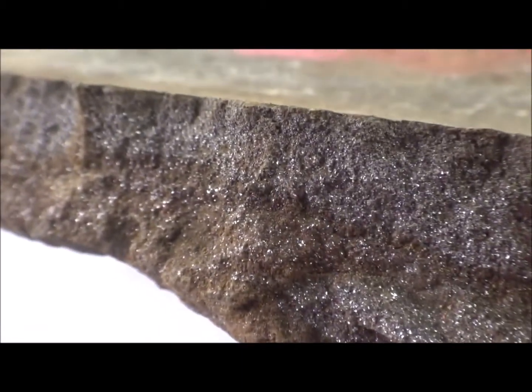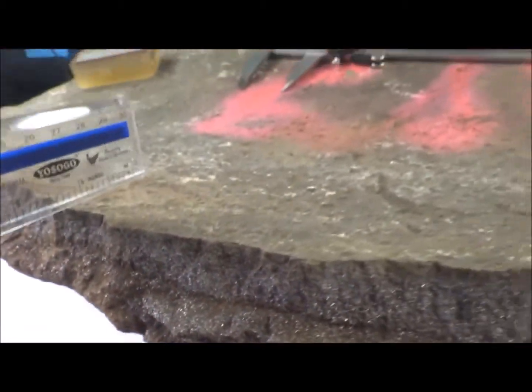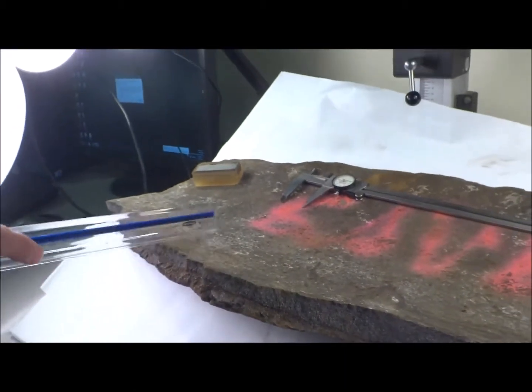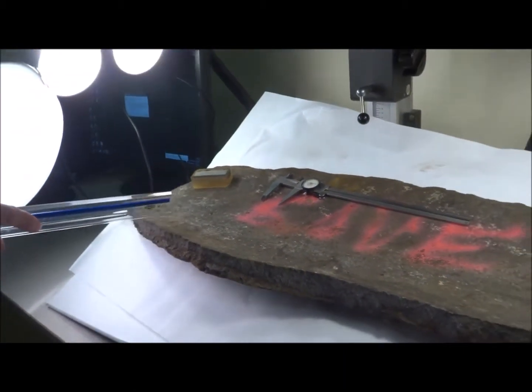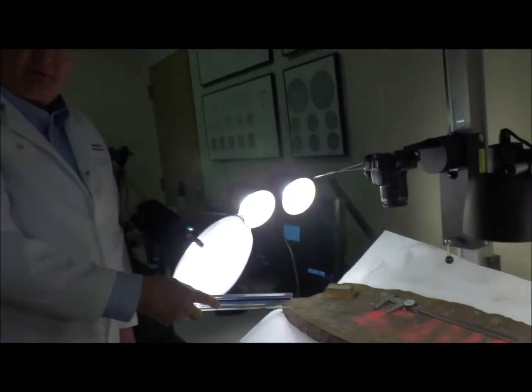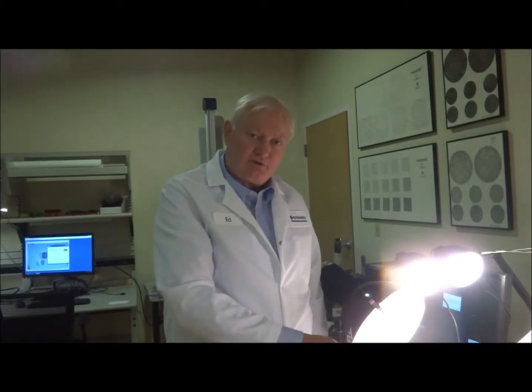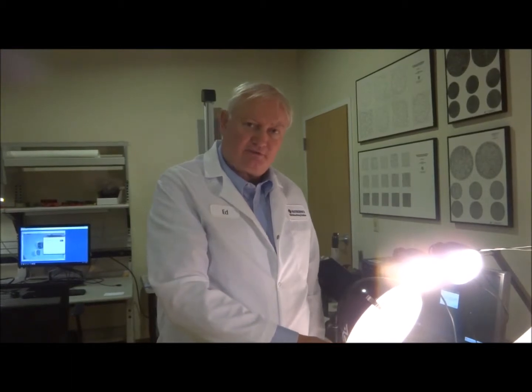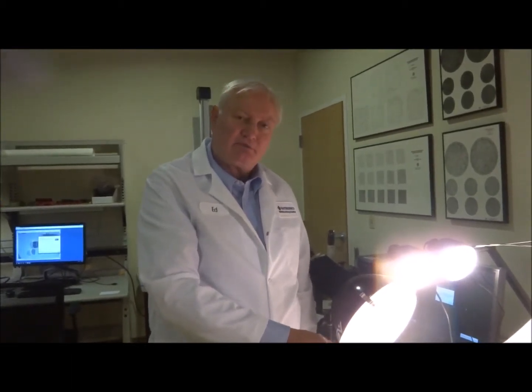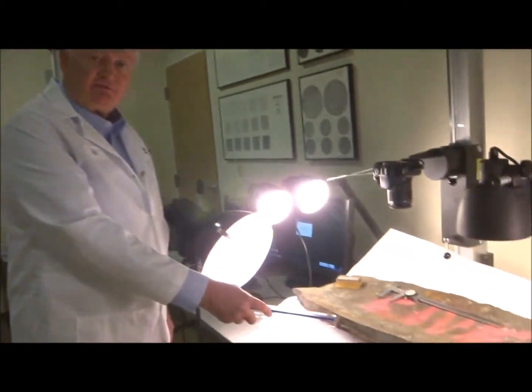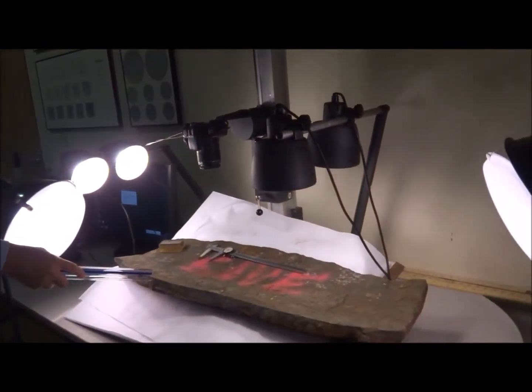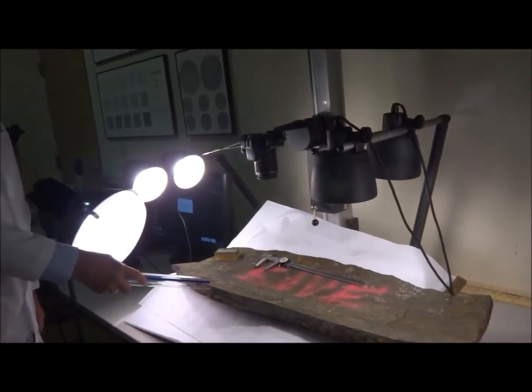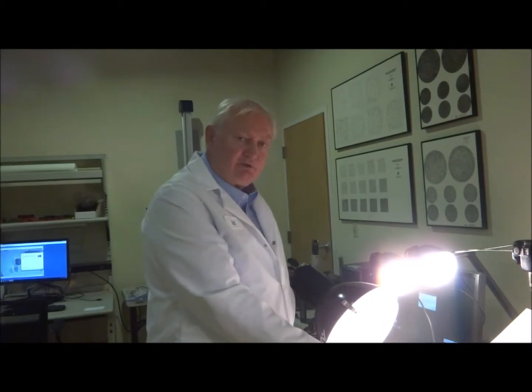So what Matergenics will do is make cross sections to look at the microstructure of the pipe. Being 90 to 100 years old, these pipes were cast differently than modern pipes. Modern pipes are usually centrifugally cast. However, 100 years ago, they were generally statically cast in a vertical direction. Because of the materials and the processes, the microstructure and properties of these pipes can vary. Therefore, we will look to see if there's anything in the metallurgical structure or microstructure of the cast iron pipe that could contribute to brittleness and failure after this much of the wall thickness is lost due to corrosion.